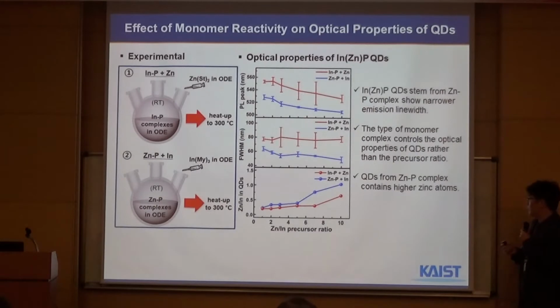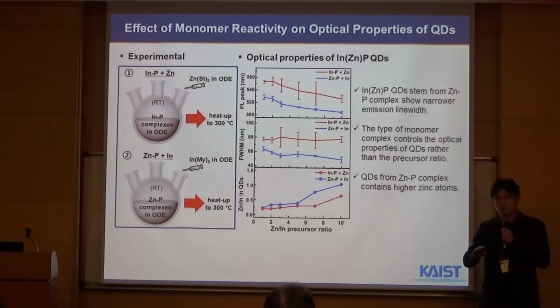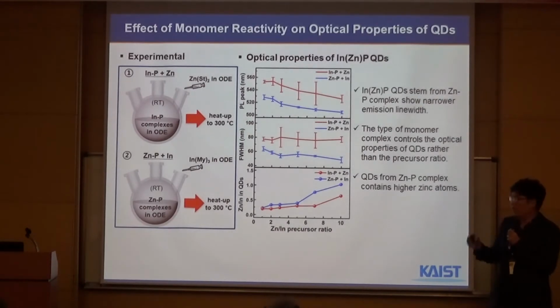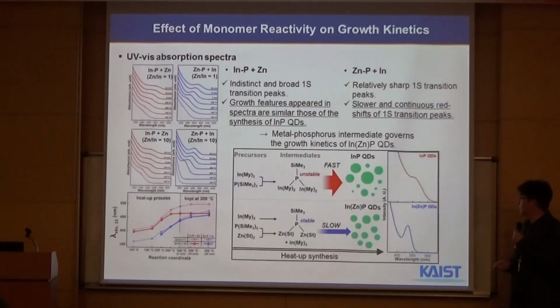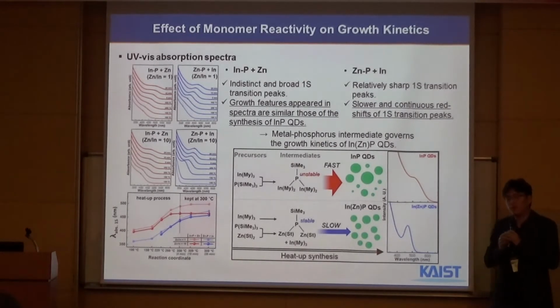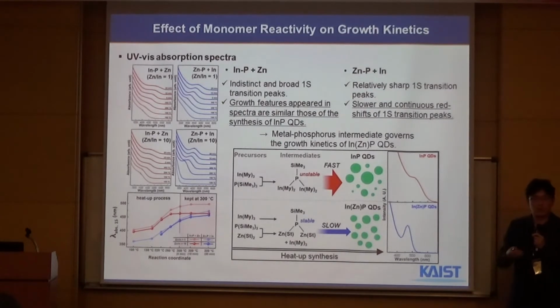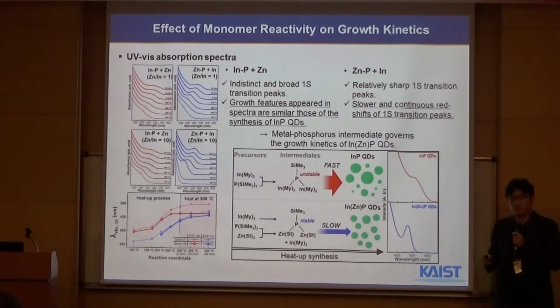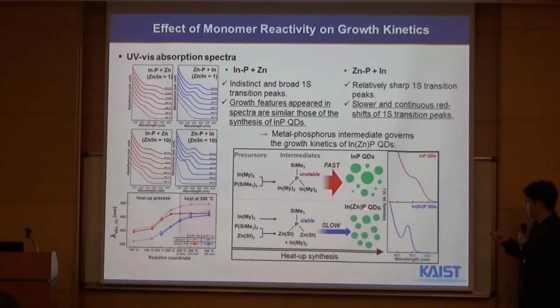So the bottom line is when you introduce zinc, because it's going to change the way the precursor intermediate species is formed, it's going to now change reaction kinetics, and therefore you get narrow emission like this. And so this is the quick overview of indium phosphide quantum dots when its synthesis is controlled by simple introduction of one precursor, one chemical, zinc.